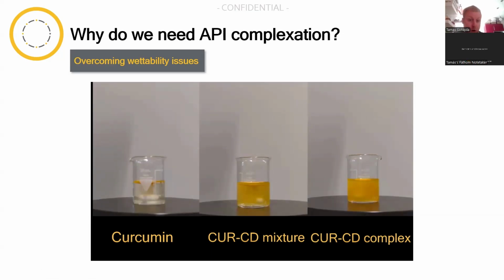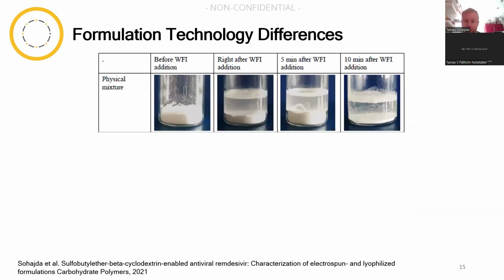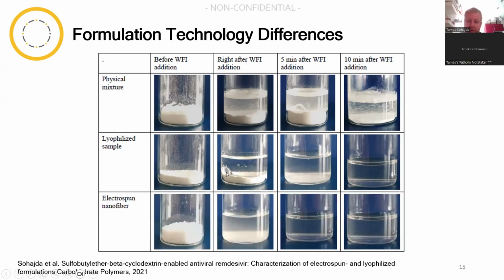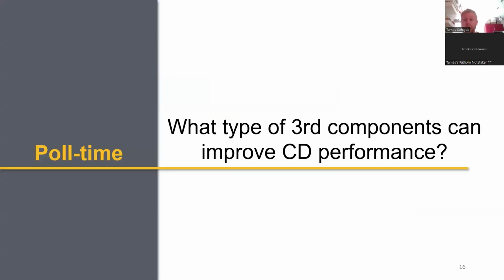So making sure that the complex is formed is critical. Also, another example to show you that if we obtain a physical mixture, this is remdesivir with sulfobutyl cyclodextrin, it's still not soluble in water, whereas a complex lyophilized or electrospun dissolves very beautifully in a short time.